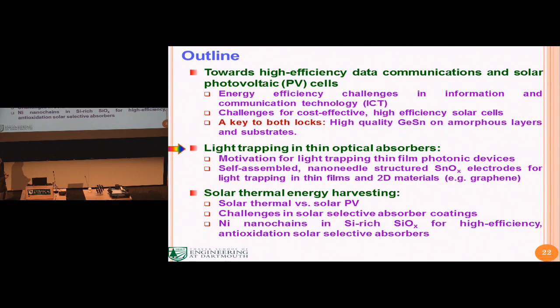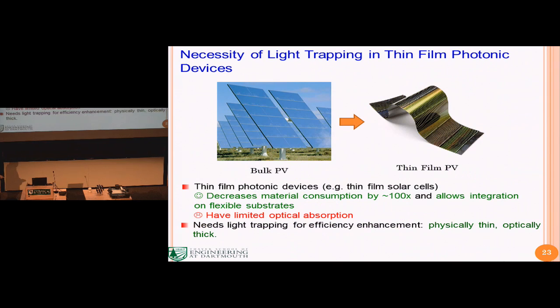So now let's shift gear and start our second topic, which is light trapping in thin absorbers. Nowadays, PV technology is trying to reduce cost while maintaining high performance. That's why you can see more and more of these bulk solar panels being substituted by thin film solar cells. Thin films use much less material. They can be deposited on flexible substrates, but on the other hand, they have very limited absorption if you do nothing on the surface because the thickness is too small.